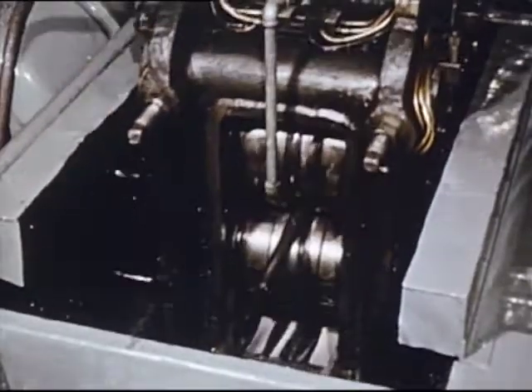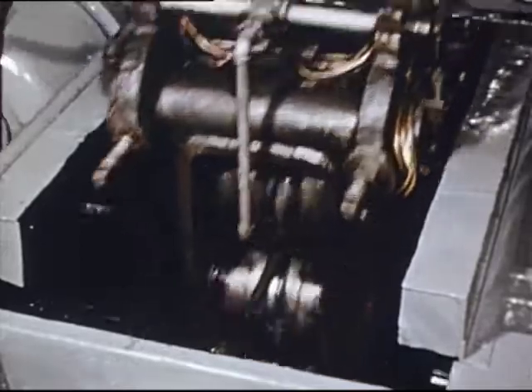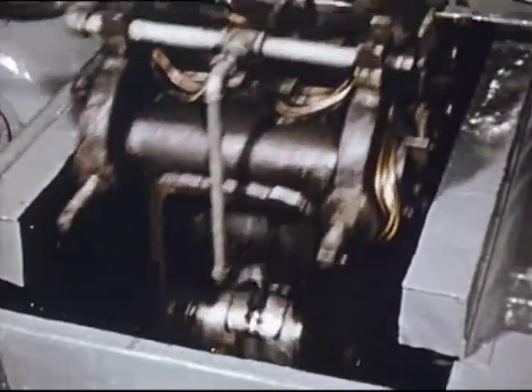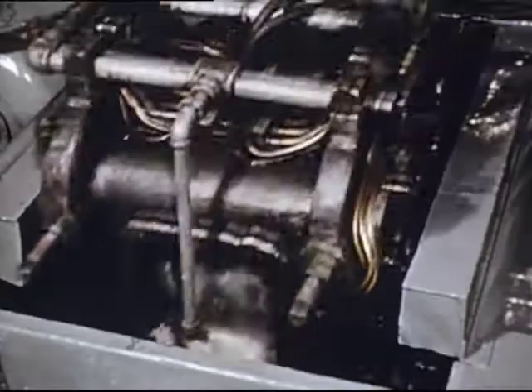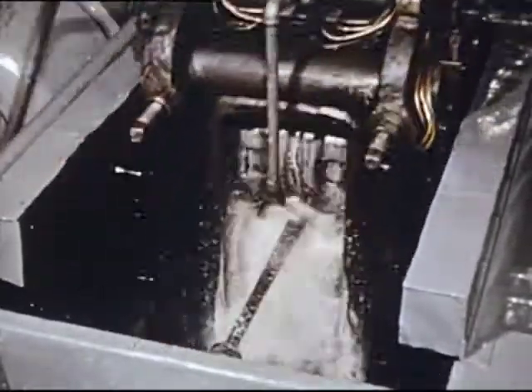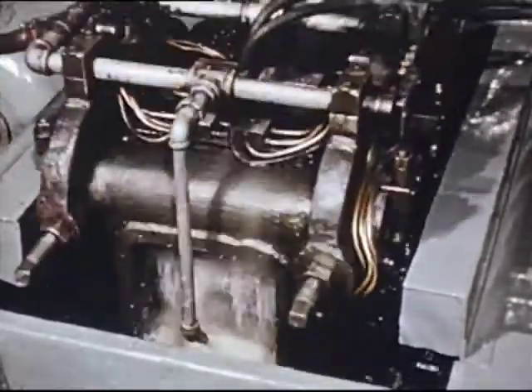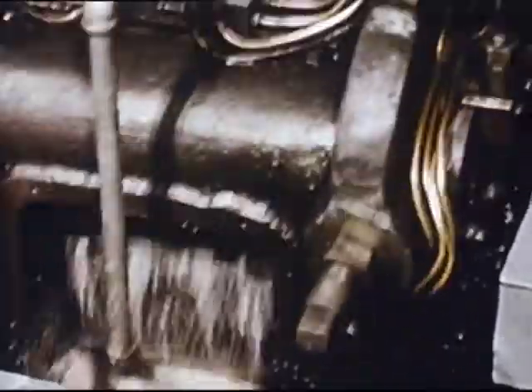Seamless tubes reduced by the tube reducer method may be shipped as finished product, but at Michigan Seamless, they are usually further processed by cold drawing to obtain the desired finish, size, and physical requirements. Tube reducing allows better control of concentricity and greater work hardness, and the combined tube reducing cold drawing process allows the best control of quality, greater flexibility of size, wall, and strength, and produces the best all-around quality of any known process.